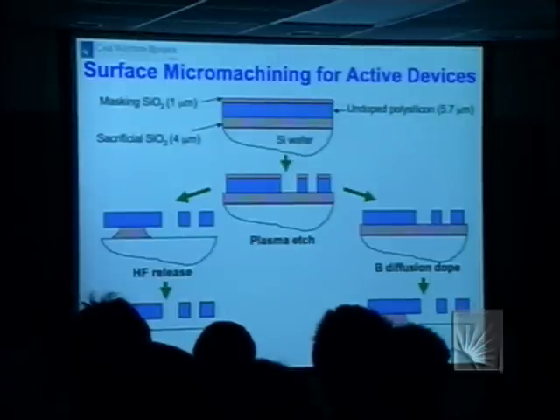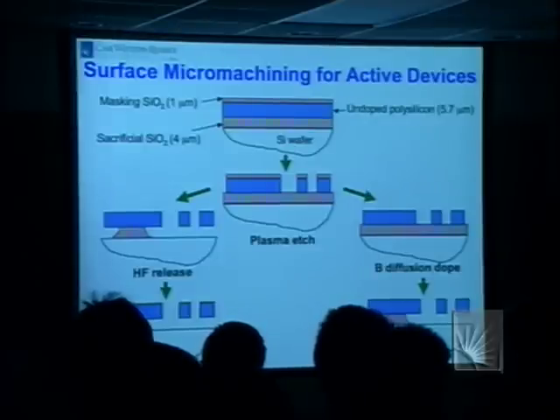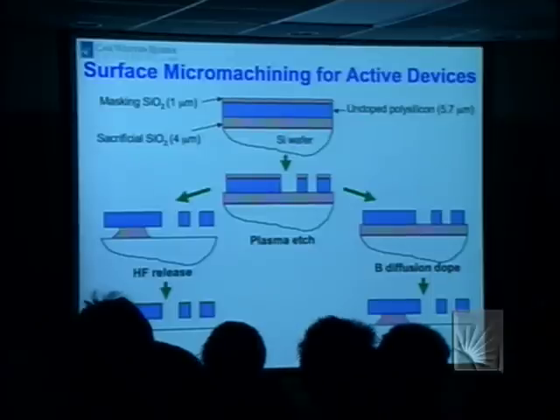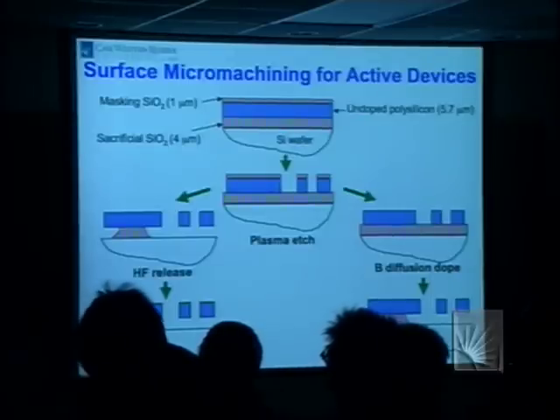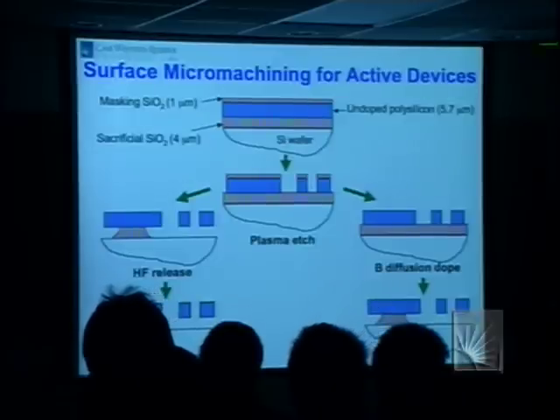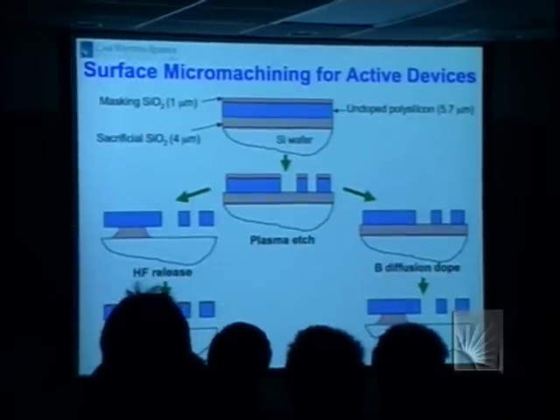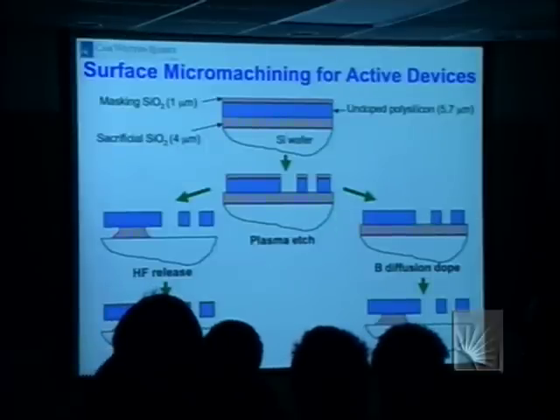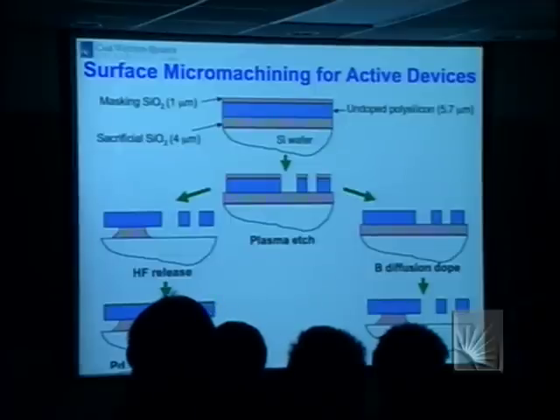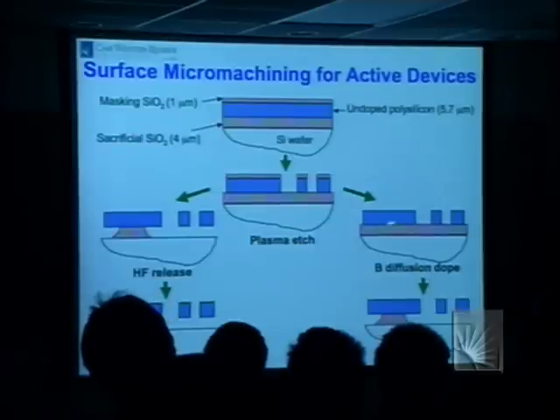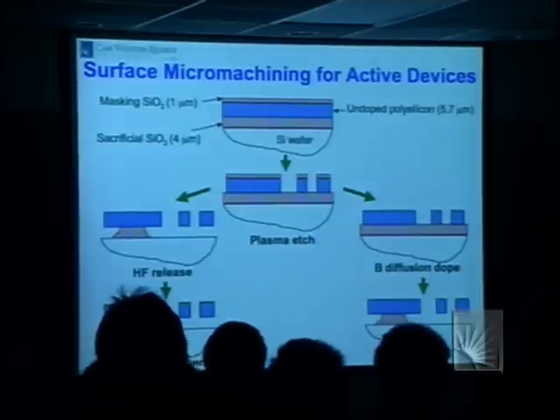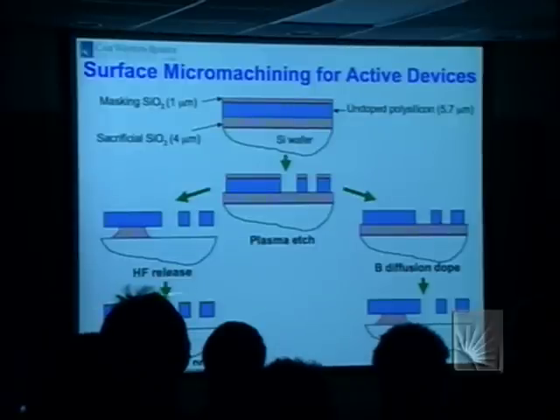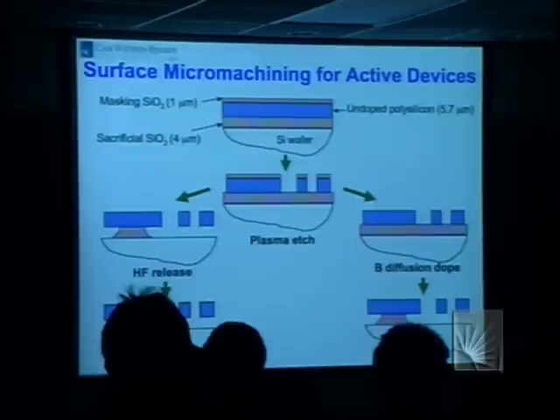Okay, well, we also are interested in active devices, and this is where I would say MEMS allows folk like me to do experiments which wouldn't be possible by conventional means. So this is the same kind of technology I told you about earlier, except we show here that we need to have conducting, semiconducting silicon, to do electrostatic actuation. I'll show you that in the next device. And you can do it either by, at this stage in device preparation, heating in a boron-containing source as the way you make transistors, or, for most of our devices, it was simpler to just sputter deposit a very thin film of palladium, and that allowed the device to be sufficiently conducting.